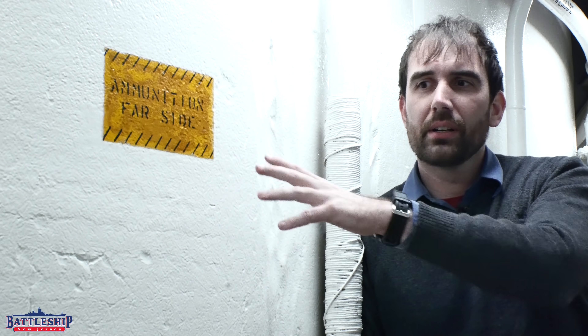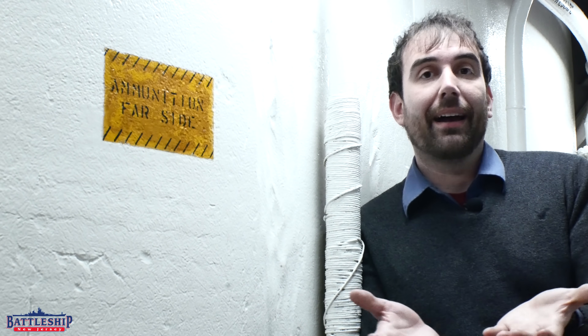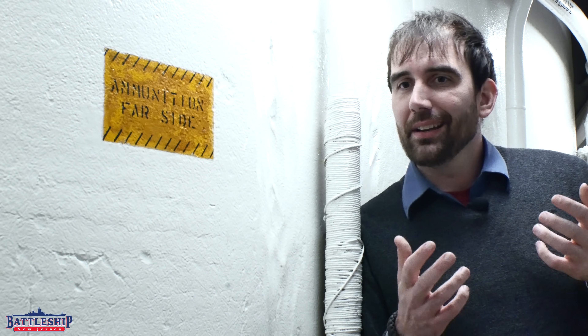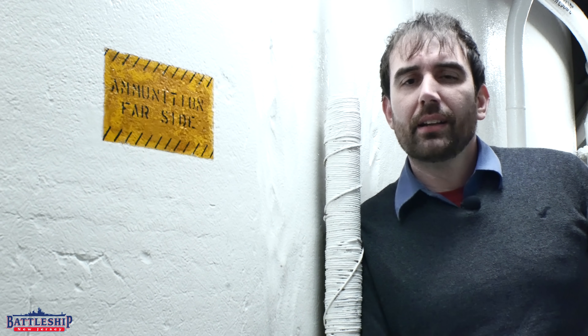If you look at the video linked in the description where we climb down into a void space to see the armored belt, that looks pretty smooth. But a curved surface like the conning tower or barbette tends to have more in it, and that's because of how these are made. Basically, you've got a bed of sand and you're digging your shape out of the sand. If that sand is not perfectly smooth, or if there's some impurity in the molten Class A armor you're pouring in, you're going to end up with cracking like this. With something curved like the barbette, you do tend to get a lot more scarring.